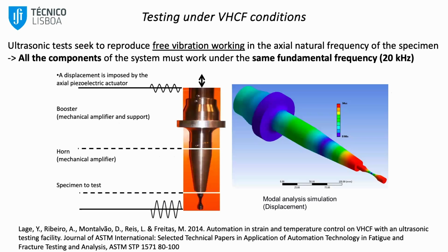Okay, so keep in mind the principles of resonance and ultrasonic fatigue tests. We are reproducing free vibration work, so we are dealing with natural frequencies. In this case, the whole set of components should be working at the resonance frequency, the fundamental frequency at 20 kilohertz. So we have here the piezoelectric actuator, then we have the booster, the horn, and at the tip, we have the specimen that you want to test, to evaluate the material.